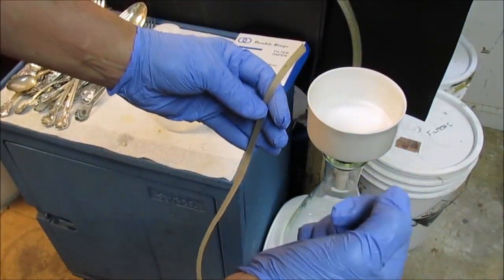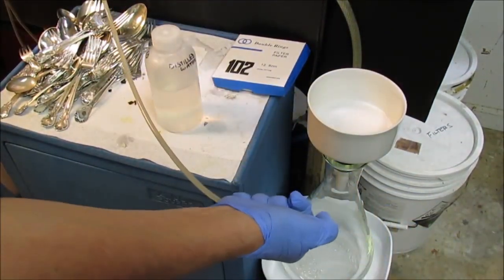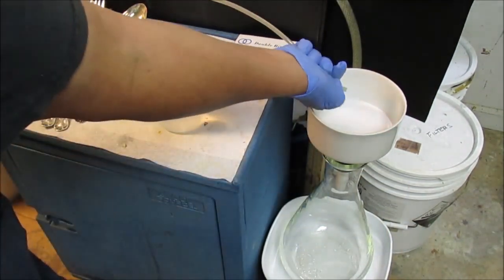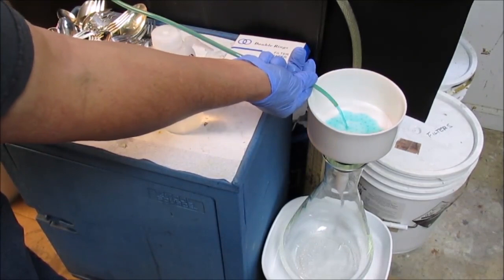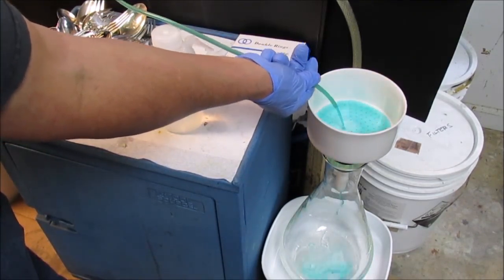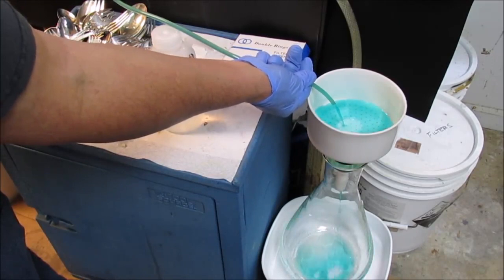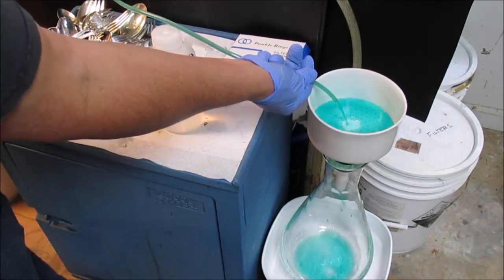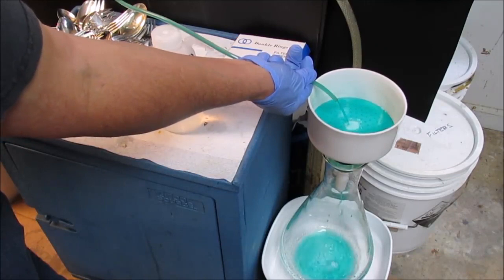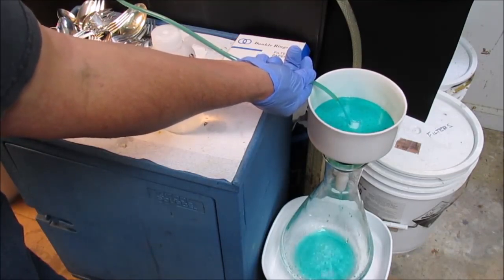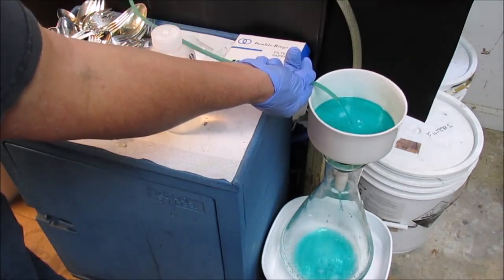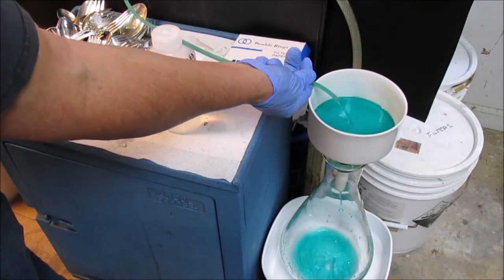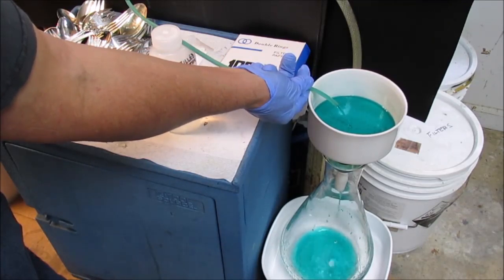Put the end of my thumb over the tube. Stick the other end up here in my solution, let my finger off the tube, and then siphon the silver nitrate solution down here into the funnel. It's better than pouring it. If I was to pour it, some of the contents has settled in the bottom of this beaker. Pouring it over into the funnel, into the filter there, would cause some sediment to come over and would quickly load up that filter paper. So siphoning out like this is much better.